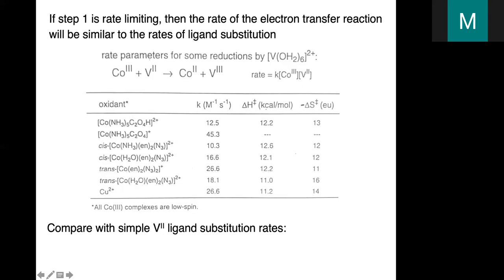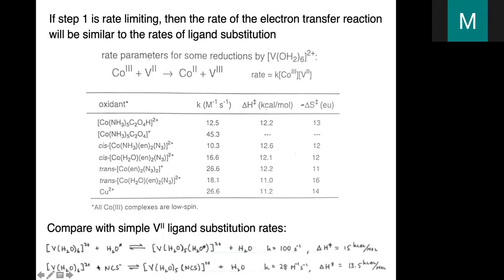So if we look at, for example, water displacing a water ligand on vanadium-2, this has a rate constant that's a little bit faster than shown for these reactions, but very similar. If we take, say, thiocyanate and do a substitution reaction on vanadium-2, we see a very similar rate for the reaction as to what we're seeing here. So this is highly suggestive of this dissociative ligand substitution at the vanadium-2 center to form the precursor complex being the rate limiting step. Right? And you can see thermodynamic parameters measured for these reactions as well.